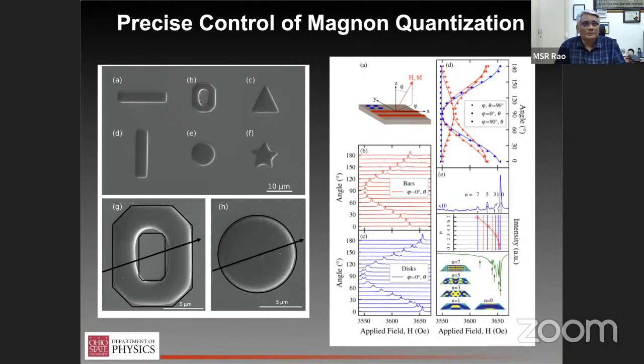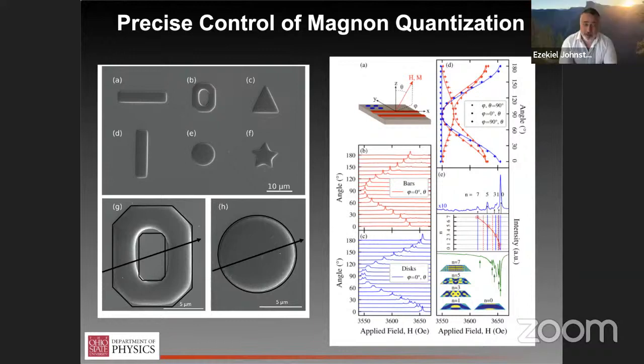I think there's a question in the chat box, Praveen. Yeah, there's one question from Sriram TN, and he's asking: bias-induced strain seems to give better alpha values. Is that an advantage? So it absolutely would be, but unfortunately, they give worse values. I mean, it's confusing in terms of, do I want my alpha to be big or small? But the alpha is larger by about a factor of 2 in the films that we use for the strain studies. And in fact, that's just a measure of that particular growth and the type of substrate we needed to use to mount it to the piezoelectric.